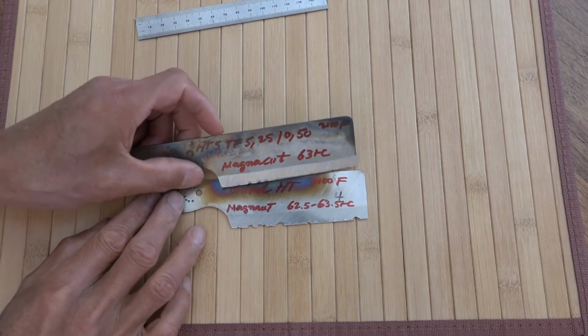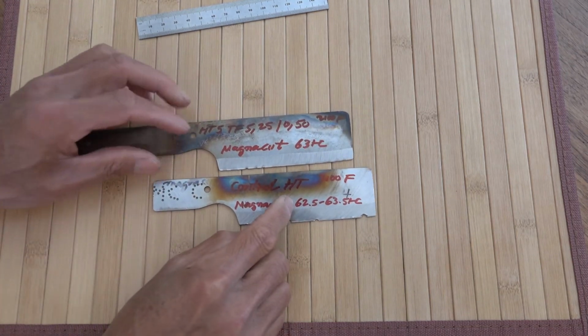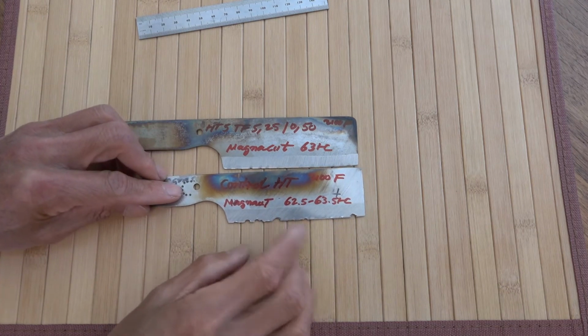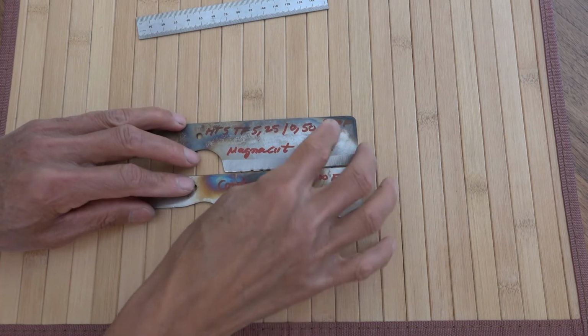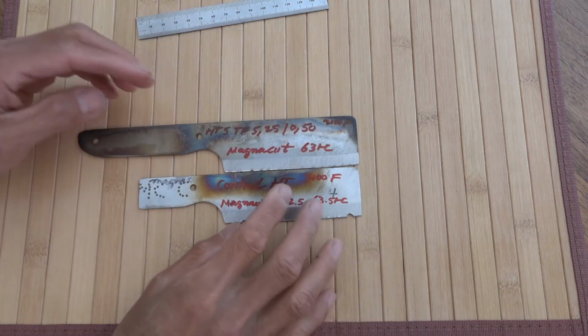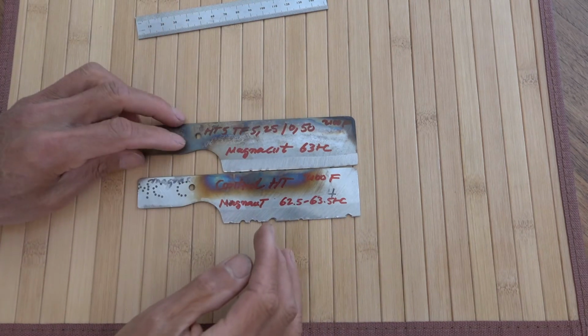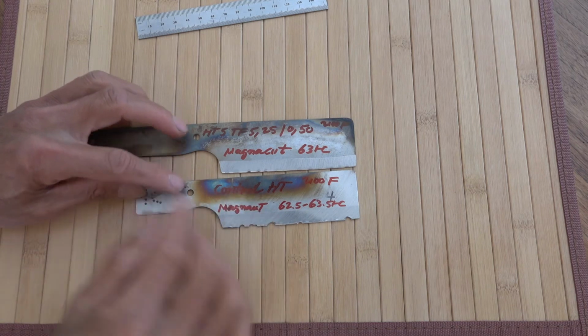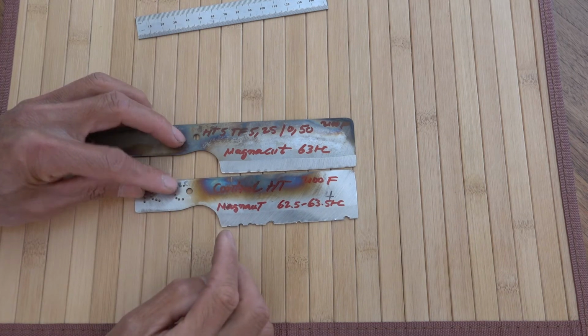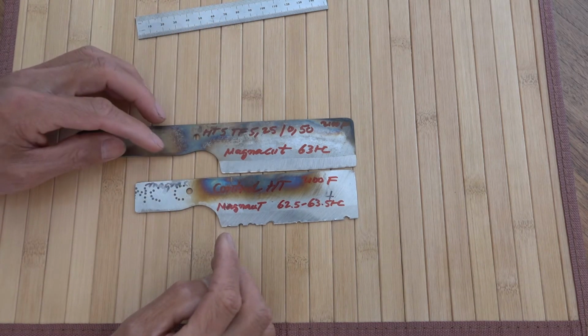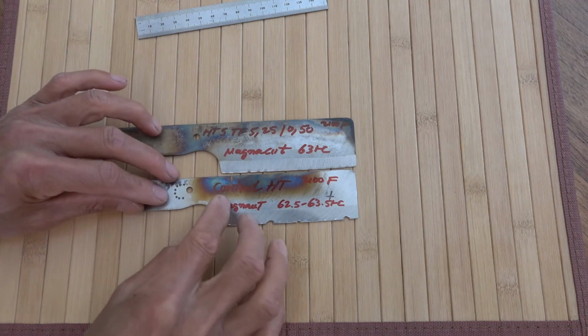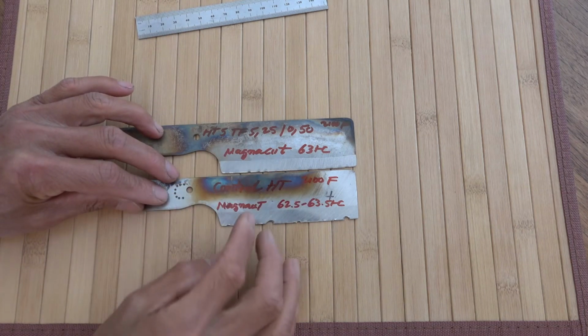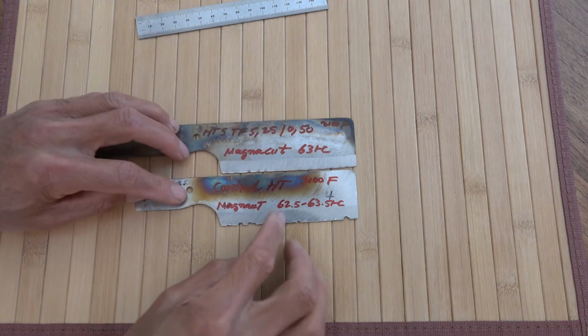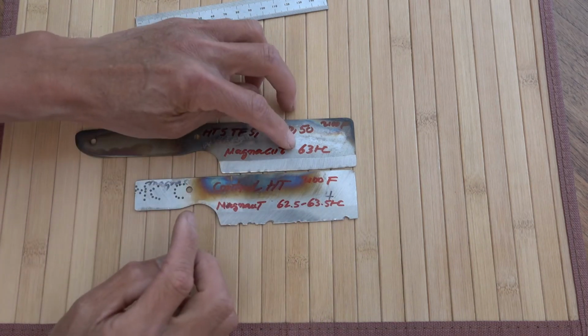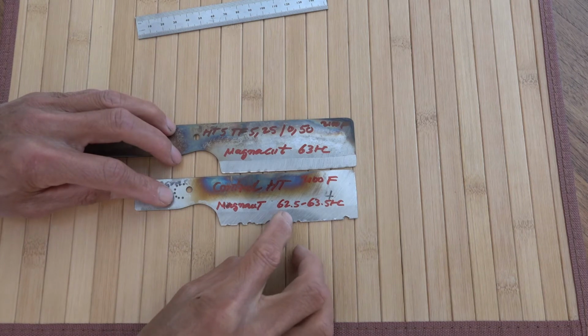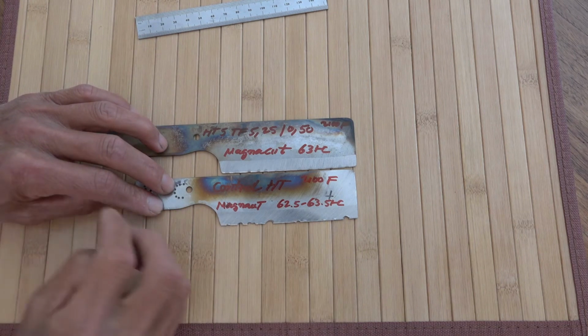This is Magnacut. This is the control right here. Austenitized at 2100 degrees, both of them austenitized in the same bath, stuck in the same oven at the same time, and then taken out. This one was taken out after 15 minutes, and this one I think ended up about 18 minutes, because I was doing something else, or 17 minutes. Both of these are more consistent than 63 Rockwell, and this is 62.5 to 63.5 Rockwell.